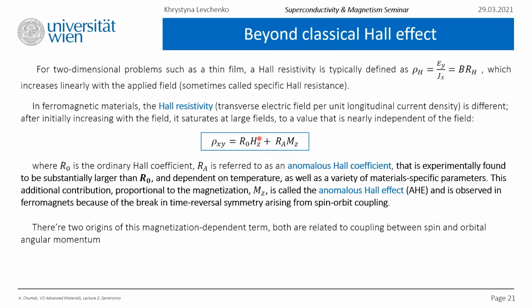For gallium manganese arsenide, it dominates in magnetic fields larger than 1 Tesla. The second term, though, is proportional, as you see, to the magnetization and dominates in lower fields, and is called the anomalous Hall effect, where Ra is the anomalous Hall coefficient. Ra depends on the material's parameters and, in particular, on the longitudinal resistivity.